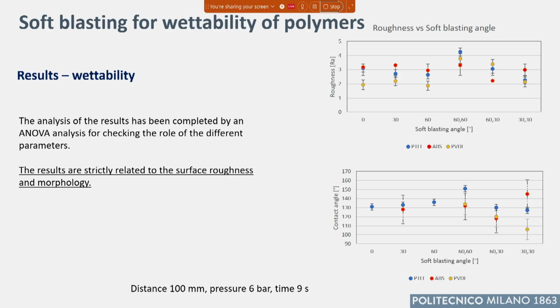And we see here that in these two graphs, in the abscissa we have the soft blasting angle, that is the inclination, the direction of the cone of impact with respect to the normal of the sample, and then we have the roughness and the contact angle. We see that the roughness is clearly different by changing the parameter, but also the water contact angle is clearly influenced by the roughness itself. Reaching as a maximum value 150 degrees, it means that you are in the field of the superhydrophobic surfaces.